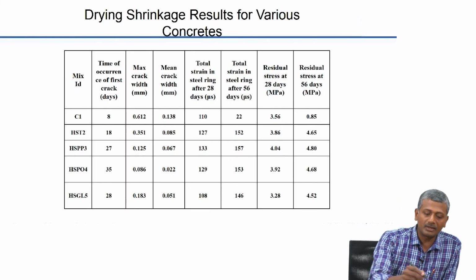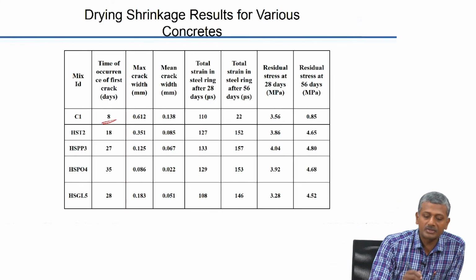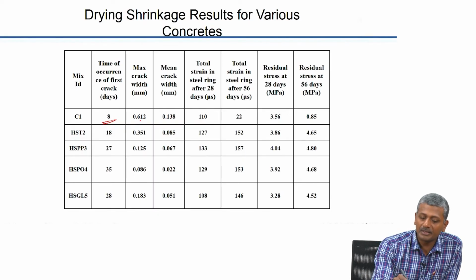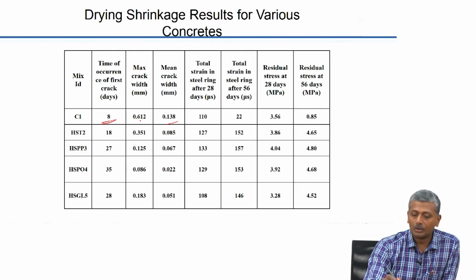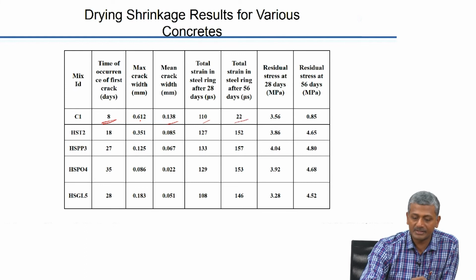So, for the control concrete, the time of appearance of the first crack was 8 days. The maximum crack width was 0.6 millimeter, mean crack width was 0.13. Total strain in the steel ring was 110 microstrains after 28 days. Strain in the steel ring was 22 after 56 days. Residual stress at 28 days is 3.5 megapascals.